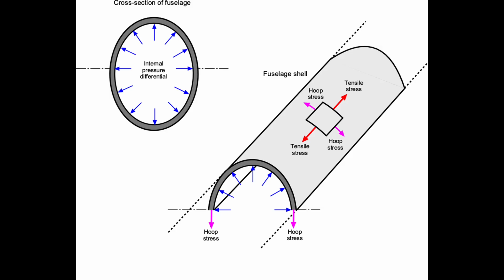From these failures emerged a new discipline. Full-scale fatigue testing became mandatory, with fuselages cycled thousands of times in test rigs that simulate years of service before an aircraft ever carries passengers. Window geometries were redesigned with rounded corners to reduce stress concentration. Materials science advanced, producing alloys with better crack resistance and predictable fracture behavior. Inspection techniques evolved from visual checks to non-destructive testing methods capable of detecting cracks before they reached critical length.